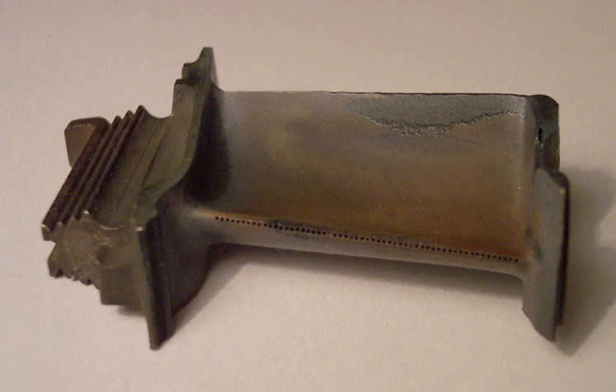Topic: oxidation in superalloys. For superalloys operating at high temperatures and exposed to corrosive environments, the oxidation behavior is of paramount concern. Oxidation involves chemical reactions of the alloying elements with oxygen to form new oxide phases, generally at the surface of the metal. If unmitigated, oxidation can degrade the alloy over time in a variety of ways, including sequential oxidation, cracking, and spalling of the surface, leading to erosion of the alloy over time. Embrittlement of the surface through the introduction of oxide phases, promoting crack formation and fatigue failure. Depletion of key alloying elements, affecting the mechanical properties of the superalloy and possibly compromising its performance.